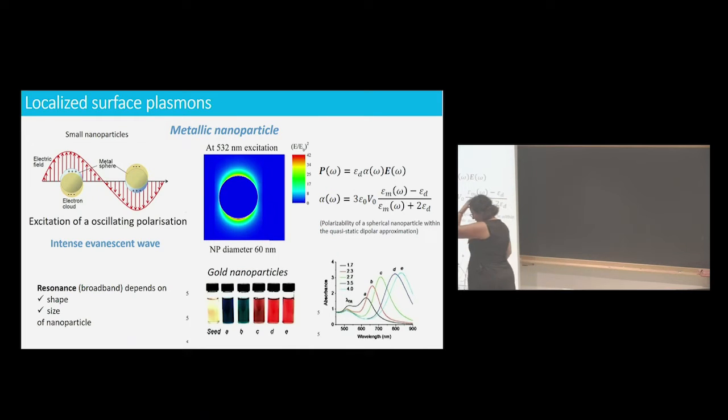So I discussed the infinite surface. Now I want to discuss the case of the metallic nanostructure. In that case, I take a small nanostructure, a gold ball for example, diameter 60 nanometers, and I excite it with an electromagnetic wave which is vertical in this direction. What I observe is that in this direction, I have extra intensity here and here. This is a kind of antenna effect.